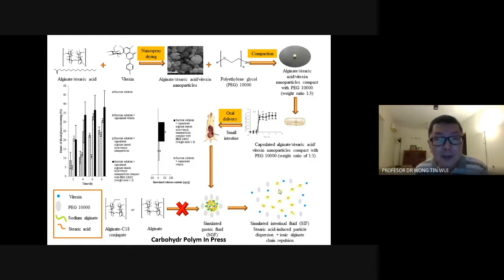The nanoparticles may be in clumpy form, but due to the stearic acid that can exert particle dispersion or particle wicking property, it can disperse the particles and perhaps even destroy the particle structure, releasing the vitexin into the intestinal regions to interact with the alpha-glucosidase. So this is the entire mapping of the mechanisms of the nanoparticles.